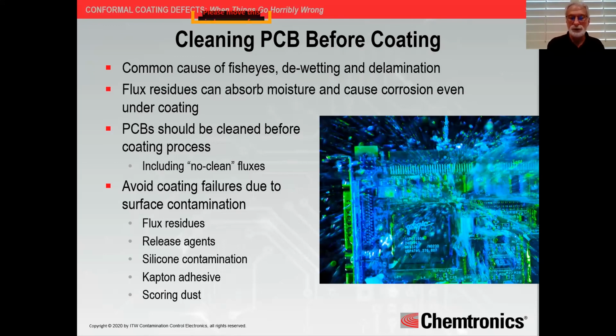So we recommend that your assemblies be clean before your coating process, and this is including no clean fluxes. And a little word about no clean fluxes: no clean doesn't mean you shouldn't clean. The reason that no clean fluxes are called no clean is because the residues do not, according to the manufacturers, contain any ionic ingredients or any ionic portions of that residue that can promote dendritic growth. However, no cleans, as well as a lot of other fluxes, can cause reactions with the coating, cause adhesion issues.